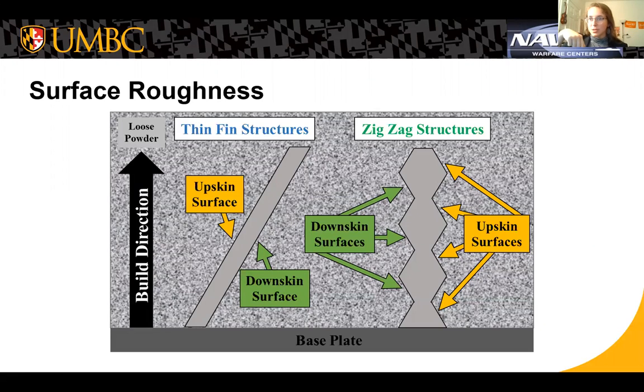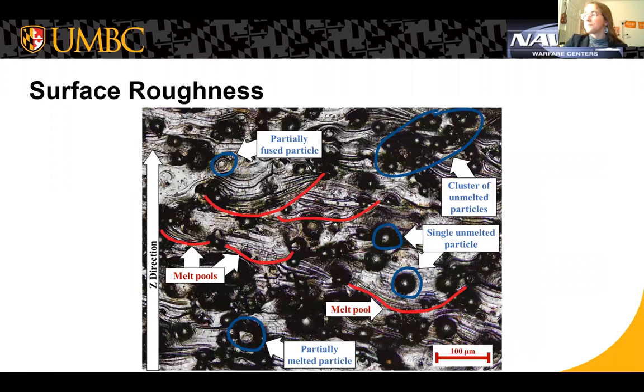And as the laser is going down, that means that there's very little room between the fused layer and the particles underneath. The upskin surface doesn't have that as much. There are some particles that rest on top. And you can see that it's both for thin fin and zigzag structures.